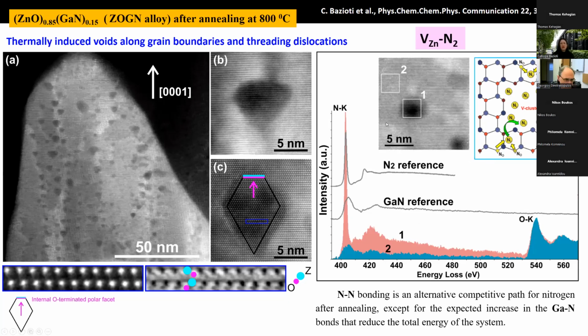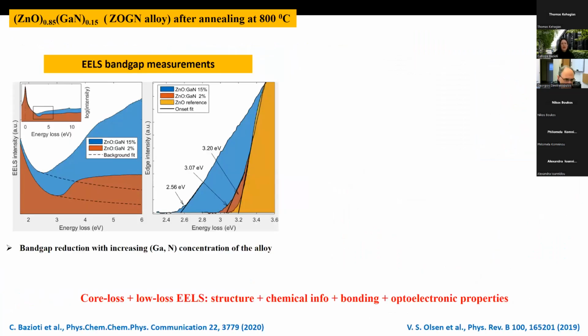So a main question for us is to understand if this redistribution and rearrangement in the nitrogen bonding can affect the bandgap properties, the bandgap values of our films. In this case, low loss EELS was very helpful. We performed nanoscale bandgap measurements with low loss EELS.